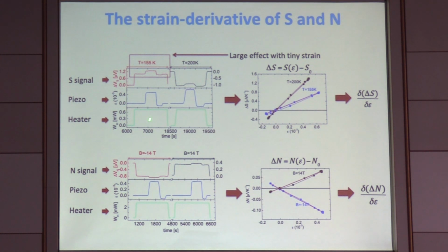So you switch on a heater, and then you measure the thermal power. You change with the piezo, apply a strain. Strains are pretty small in this case. You see here the numbers. You still see a change of the thermal power here. It goes up, goes down again. There are even funny situations where the thermal power itself changes sign, and the effect of the strain does not.